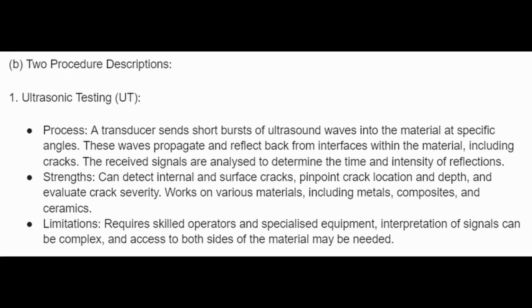B. 2 procedure descriptions. 1. Ultrasonic testing. The process: a transducer sends short bursts of ultrasound waves into the material at specific angles. These waves propagate and reflect back from interfaces within the material, including cracks. The received signals are analyzed to determine the time and intensity of reflections. Its strengths: it can detect internal and surface cracks, pinpoint crack location and depth, and evaluate crack severity.